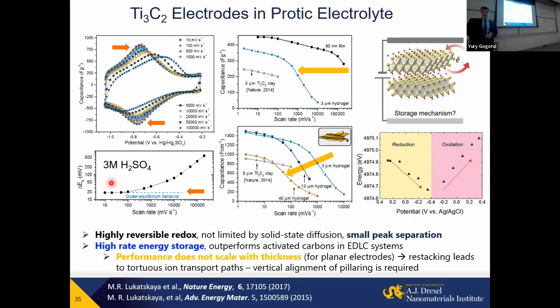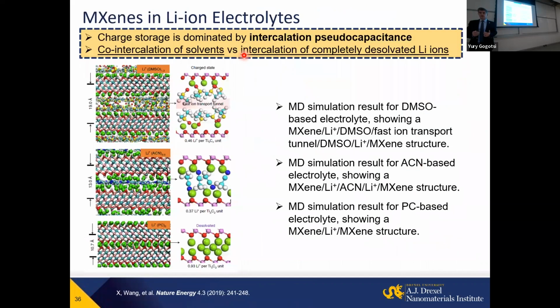But moreover, this peak, while it shifts, stays up to a rate of 100,000 millivolts per second, 100 volts per second. So for 1 volt, it's a 10 millisecond charge. It means that, in fact, in batteries we're not limited by redox reaction rate. We're really limited by transport of either ions or electrons. And if we have a highly electronically conducting material, we really need to design the architecture, because as the layer gets thicker, ions move slower. There's a long pathway. But it shows fundamentally that it's possible to create the devices I'm talking about.